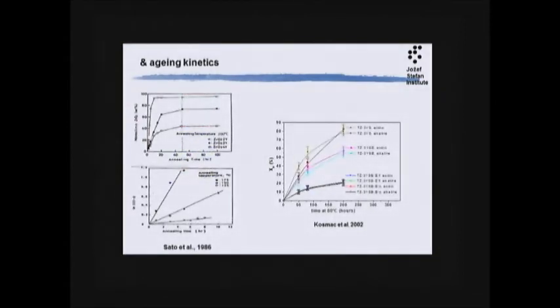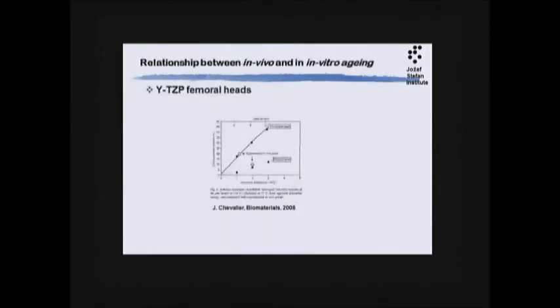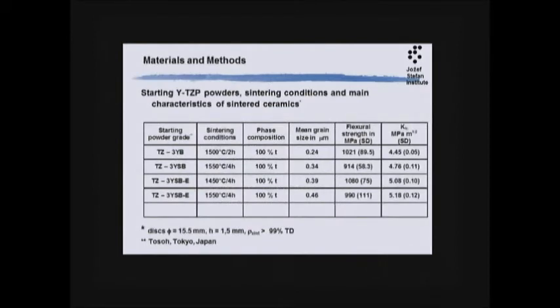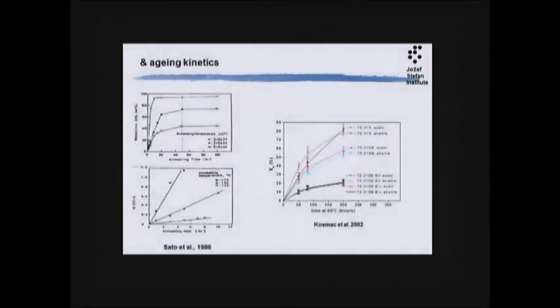Okay, some on the kinetics. The lower the yttria content, the higher will be the transformability, and the higher the temperature, the faster the transformation will occur. And we have checked this at that time. There were standard grade materials and the one with alumina added, and there is an enormous difference. So 0.25% of alumina addition indeed strongly reduces the transformation rate. We checked various atmosphere environments, but there was not such a big difference in that.